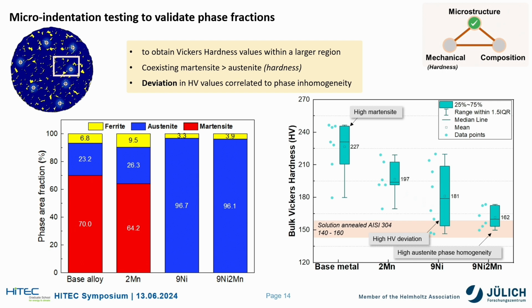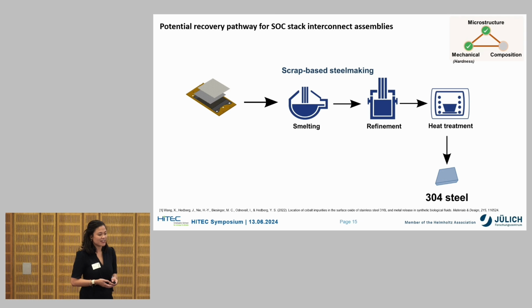Furthermore, its Vickers hardness values are falling within the expected range for a solution annealed 304 steel, so we can make a big check here in terms of achieving the hardness property of this 304 steel. So far, so good. Now we only need to see the composition.